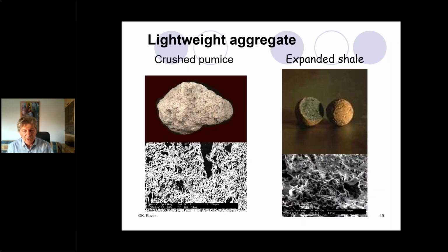And then the whole idea of internal curing is introducing, how to explain, a kind of Trojan horses, something which is acting from inside. This material or this additive or mixture can be called an internal curing agent. It should be porous because it should accommodate, it should contain some water. But please look, this water is not a part of the mixing water. It should be released slowly during the hydration process, but not immediately. And pumice, we worked a lot with crushed pumice. I will explain some results later on. And expanded shale aggregate, both of them illustrating the porous structure of the aggregate, can be nicely used as an internal curing agent.